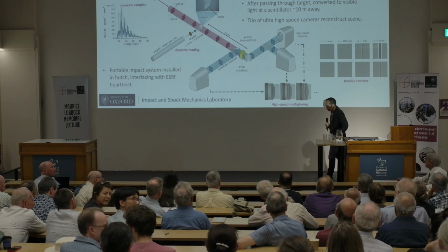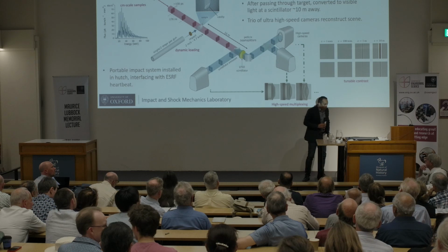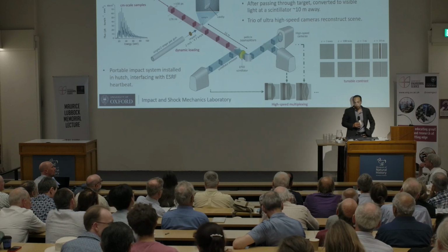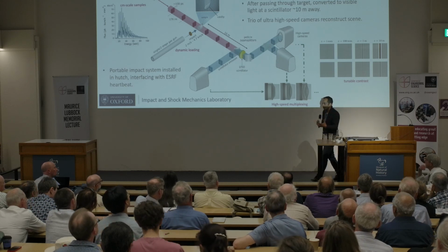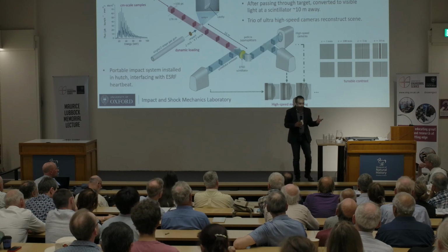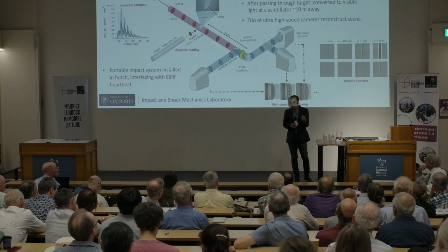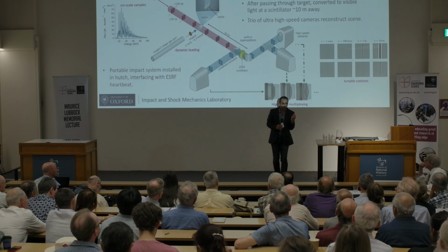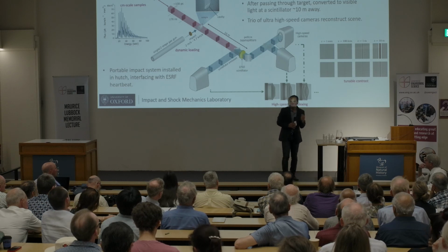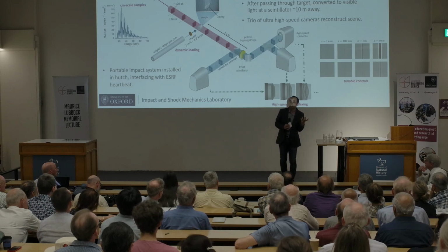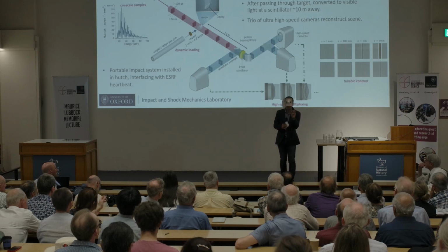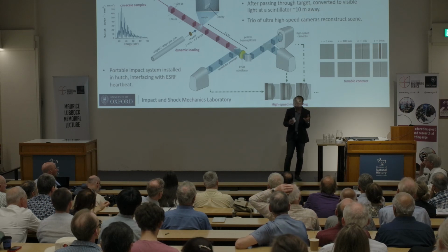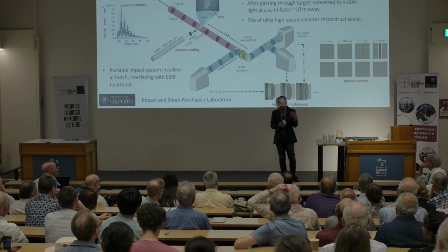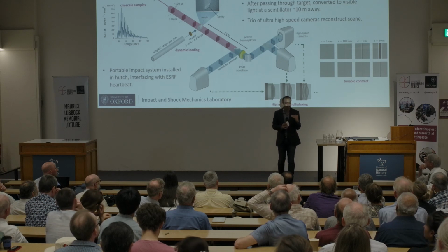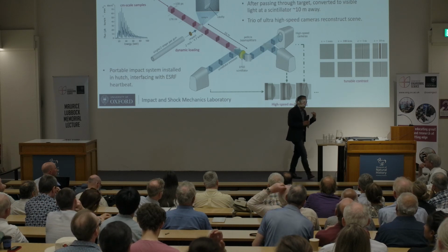Okay. Yes. So there are different ways in which you can take a perfect material or material that has defects and produce an increased number of defects, so these dislocations. One is through heterogeneous nucleation. That's, for example, classical Frank-Read sources. These would be pre-existing defects that then evolve in a certain way and emit new dislocations. And so that has a lower energy barrier. It doesn't take quite as much energy to get them to activate.